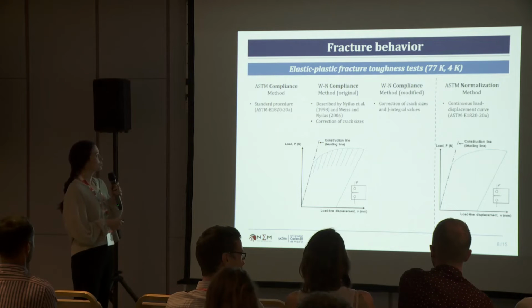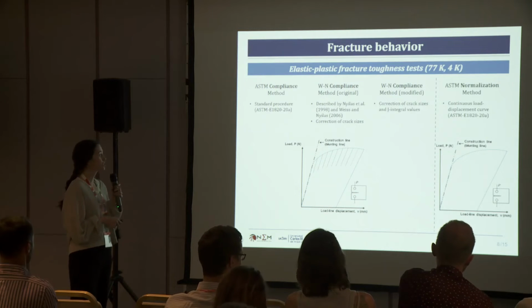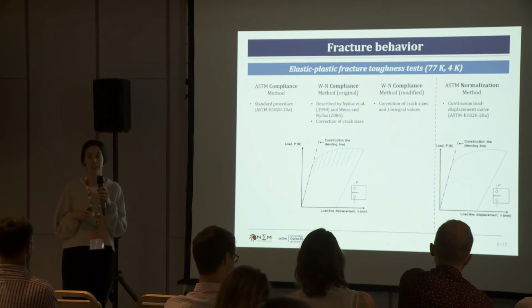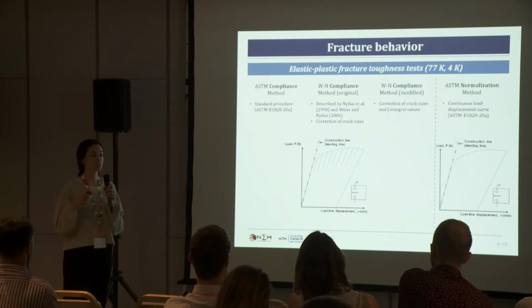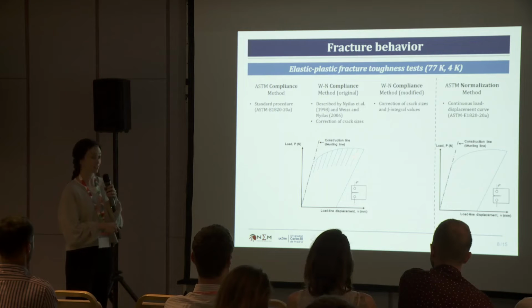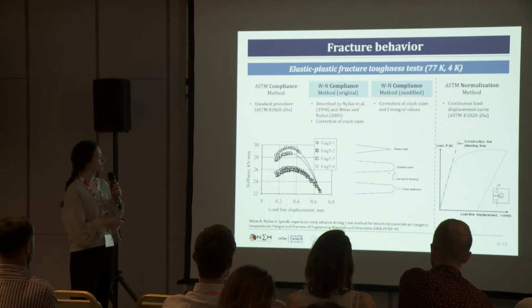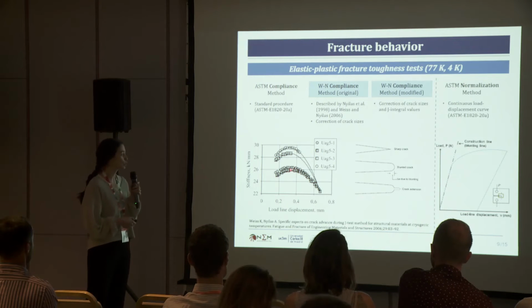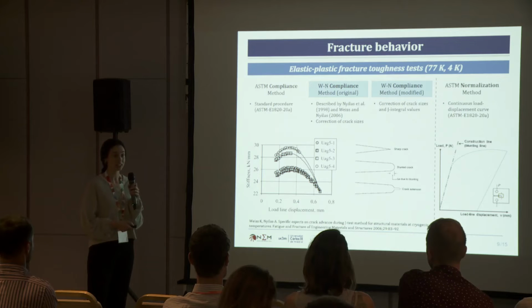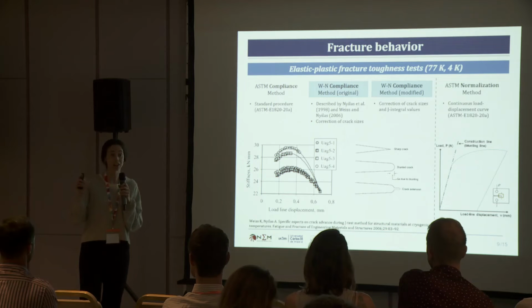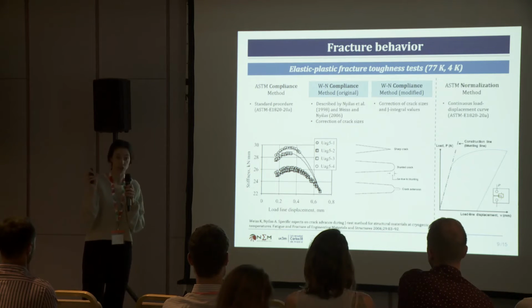The difference between the 3 compliance methods is that the first one, which is the official method described in the standard, it just assumes, it's quite easy, it just gives you the equations, and it just assumes that as the crack grows, the stiffness in the specimen decreases. So the compliance increase is what you can see more or less in this image. Now, regarding the other 2 compliance methods, this one was proposed by Weiss and Nyilas. That's why we have here the W-N. According to them, what they did realize is that the stiffness is not always decreasing, but at the initial state of the test, the stiffness is increasing, which will lead to a negative crack extension, which of course doesn't make sense. The crack is not decreasing and then increasing.